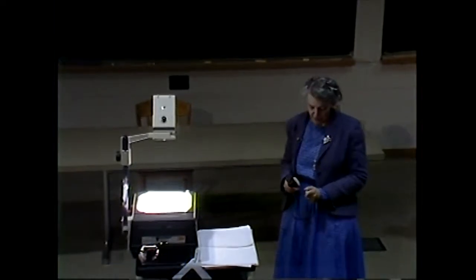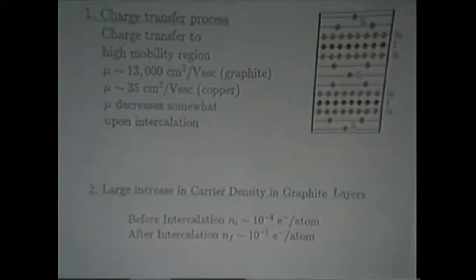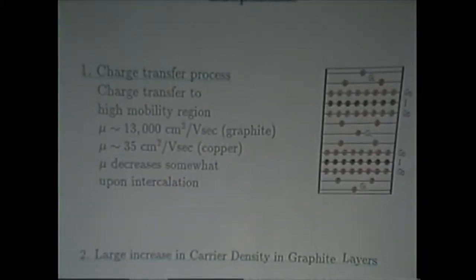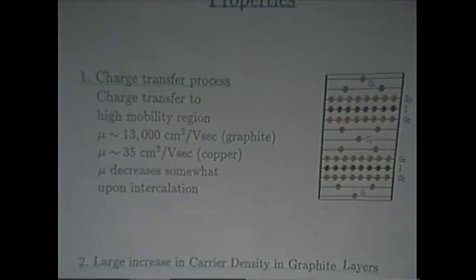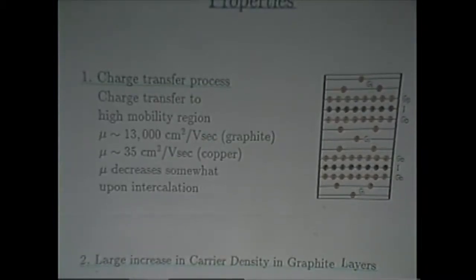in transport? I said that intercalation changes the transport properties by an order of magnitude. And then I said also that the electronic structure didn't change and the lattice mode structure didn't change. So what changed? Well, what changed was the position of the Fermi energy. I guess the students in the solid-state class have heard me say this very often, that you can change the properties of a solid greatly by changing the Fermi level, keeping the electronic structure the same. Well, how does that work?